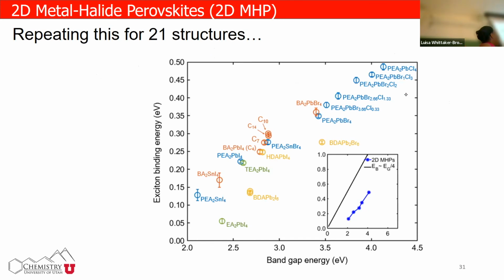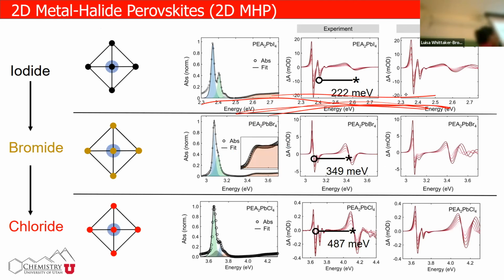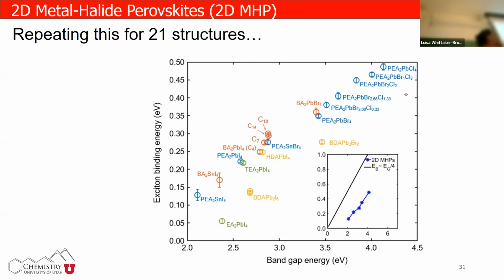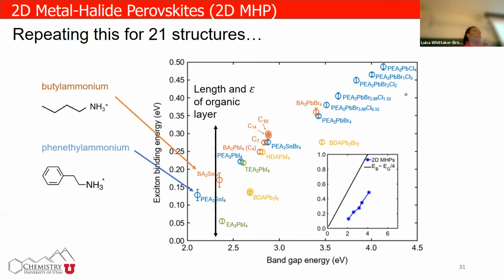The chloride is 487. Okay, so we did this for 21 other structures where we are varying the organic and the inorganic component. So we know that we have tunability according to the organic layer in one direction, and then tunability in this direction. But still, the variation that we're seeing is pretty broad because not all of them are following the line. Okay, and that is actually related to lattice effects. The way that that is related to lattice effects is through the dielectric constant, because we're not computing the right dielectric constant. We just took one random dielectric constant that we found in the literature.